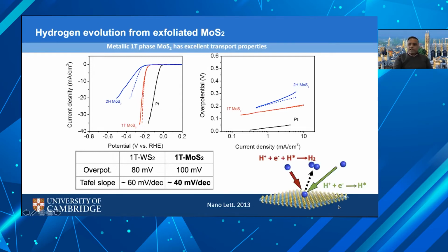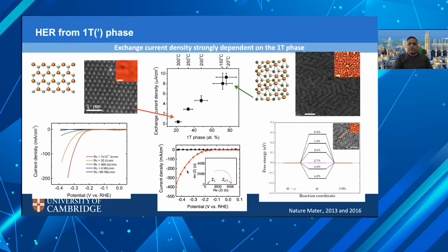So the way the hydrogen evolution reaction works is that you have your proton that is adsorbed onto your catalyst, which recombines with an electron to have an adsorbed hydrogen species on the surface. Eventually, if you have enough of these adsorbed hydrogen, they combine and evolve hydrogen. And so from the polarization and the Tafel slope curves, we can obtain the kinetics and thermodynamics of this reaction. And so I've just summarized some of the results over the years that we've reported for these metallic catalysts